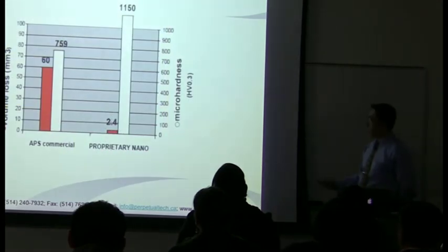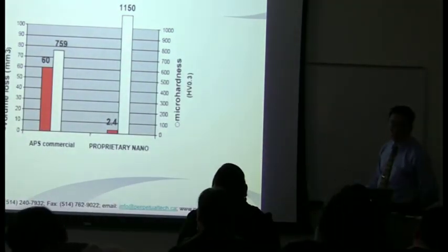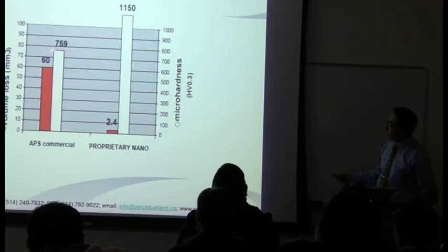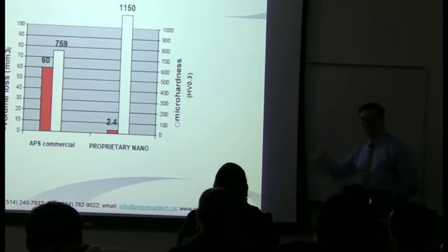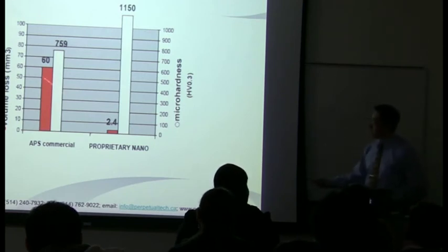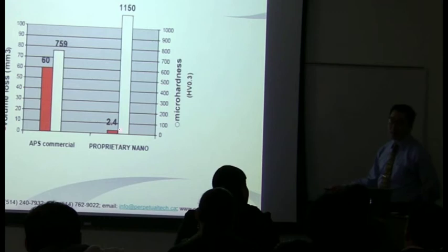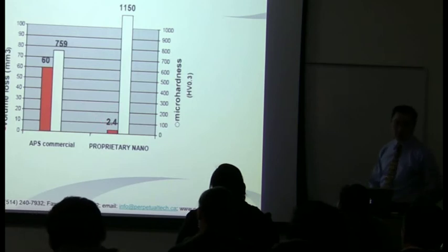Here are the results. In the orange column, you have the volume loss. White columns are your micro hardness. Now, yes, our hardness increases by about 50%. That would lead to a decrease in volume loss. But this is not what anyone expects. Even with this increase in hardness, you would not expect such a dramatic decrease in volume loss.